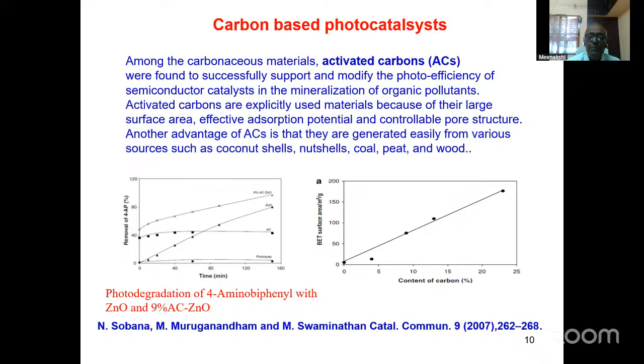That is, titanium dioxide P25 is a special type of TiO2 having about 80% anatase and 20% rutile. It's specially marketed only for environmental remediation. So we have prepared this activated carbon loaded TiO2 P25 and activated carbon loaded zinc oxide. And at that time, we did the degradation of 4-amino-diphenyl. You can see in this 4-amino-diphenyl degradation, 9% AC-ZnO is found to be most efficient when compared to the other percentages of activated carbon in zinc oxide.